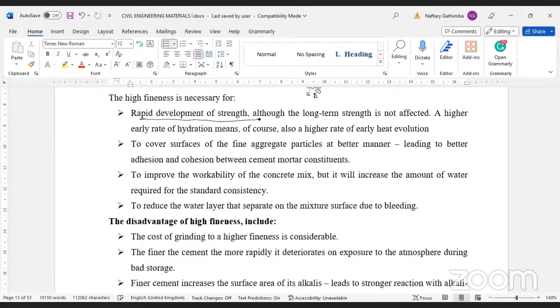Okay, so if the cement paste is highly refined, we may realize that because of the more extended surface area, it reacts quickly, and therefore we are able to obtain high early strength. Of course, if the chemical composition is the same, at the end of it, when all the ingredients have reacted, long-term strength is not affected. Whether the particles of the cement were finer or bigger, the one with the fine grains will develop strength earlier.